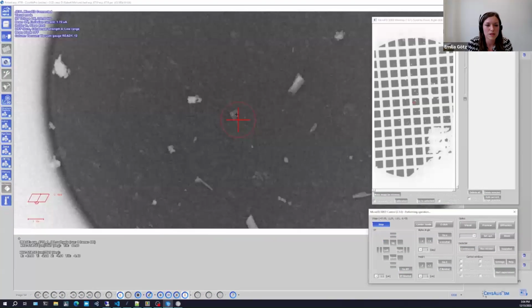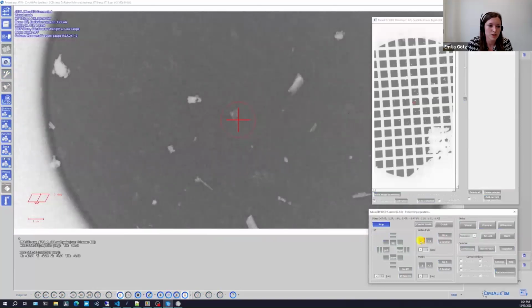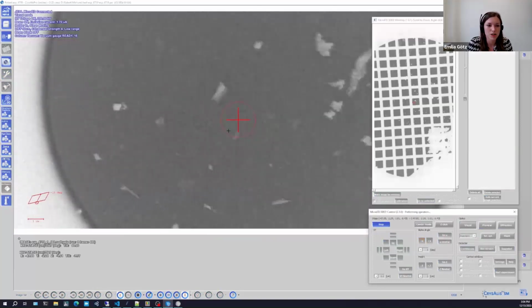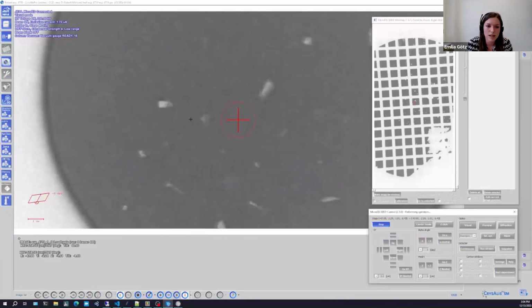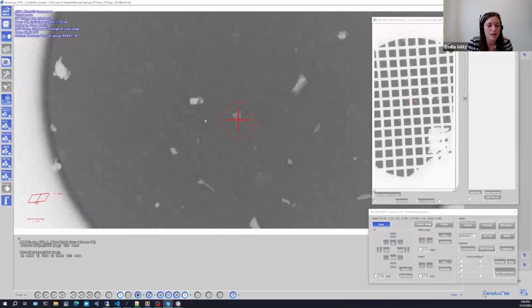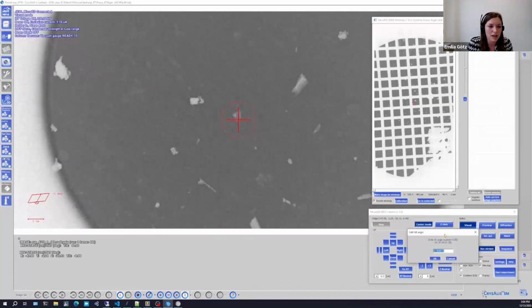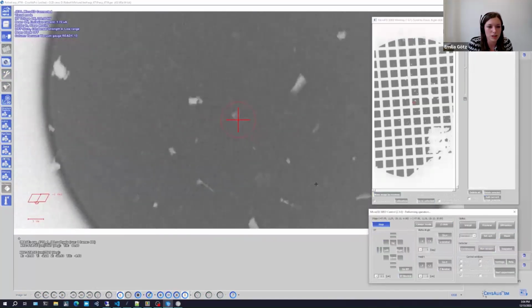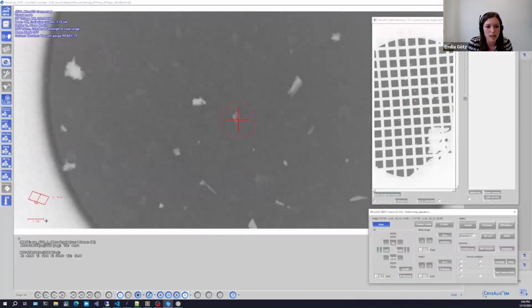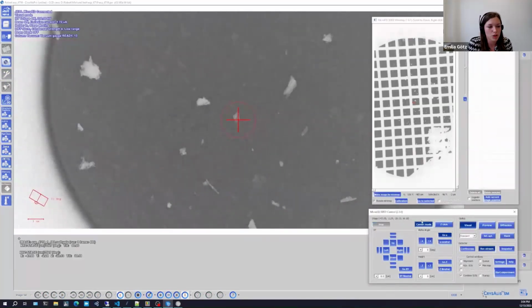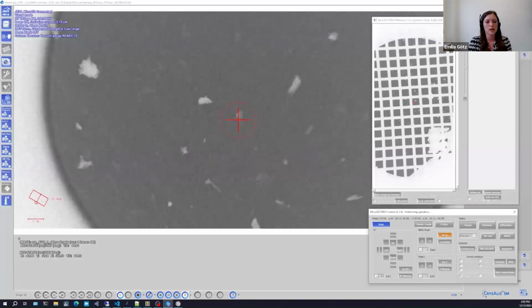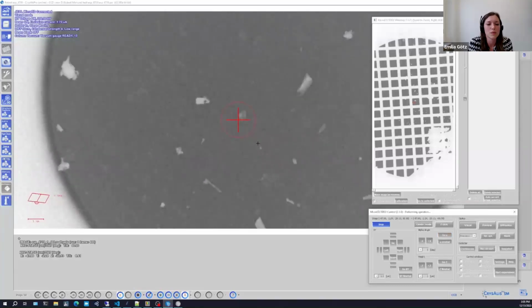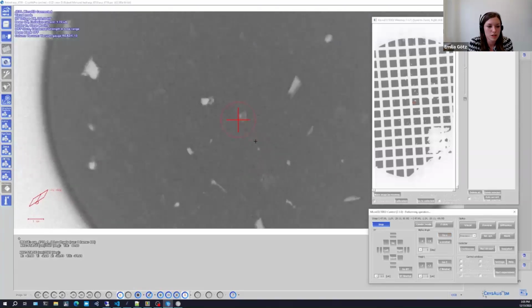And in the next step, similar to single crystal X-ray diffraction, we center the crystal on the rotation axis of the stage. And this is done by tilting the stage to a certain angle. And we have a visual indicator on the left showing us the current tilt angle, as well as the scale bar, which corresponds to 1 micron. So by using the point and click interface of the mouse wheel, we adjust the Z position of the crystal.